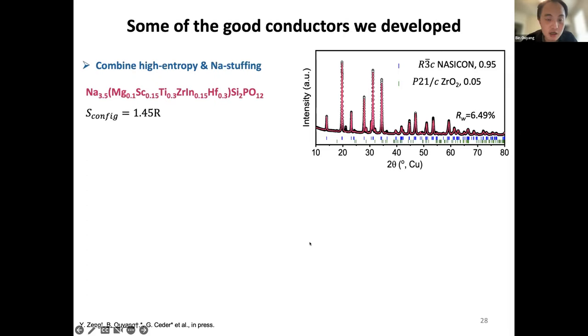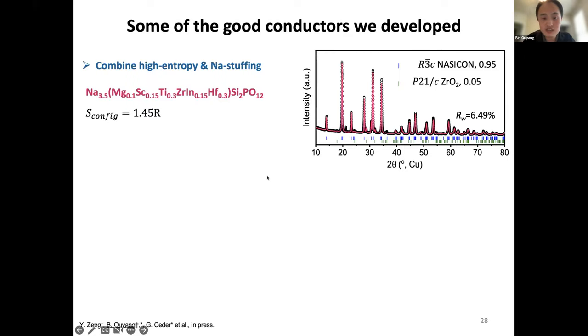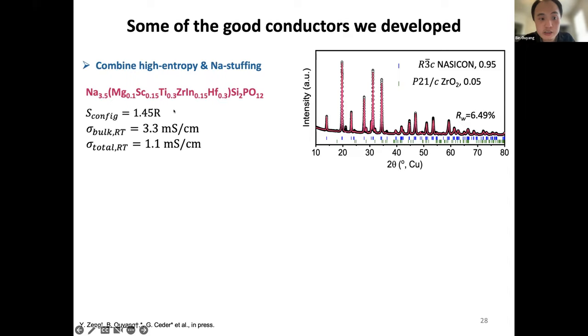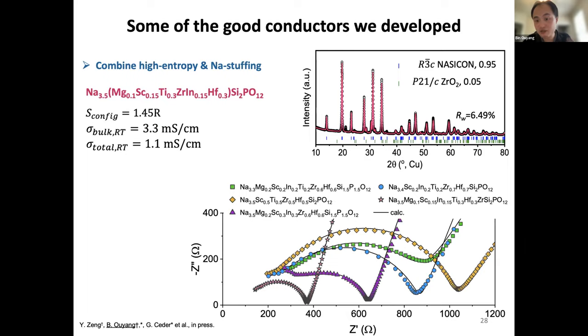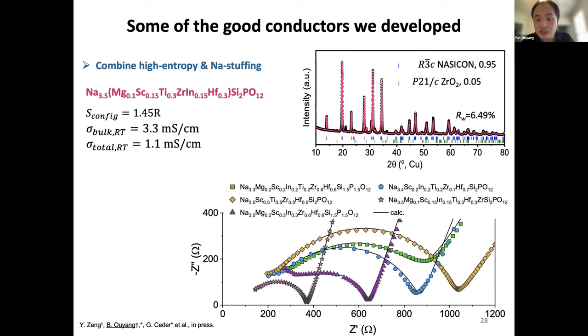On the basis of this idea, we're pushing limits to see how far we can go — taking known good materials and making them high entropy. We synthesized one sample with six transition metals showing 3.3 mS/cm bulk conductivity, comparable to one of the best oxide conductors already commercialized. We made a bunch of these high entropy materials and are happy to see that most behave reasonably — all five compounds shown, despite random-looking compositions, have ionic conductivity larger than 1 mS/cm. This means high entropy can be a generic mechanism to boost ionic conductivity.